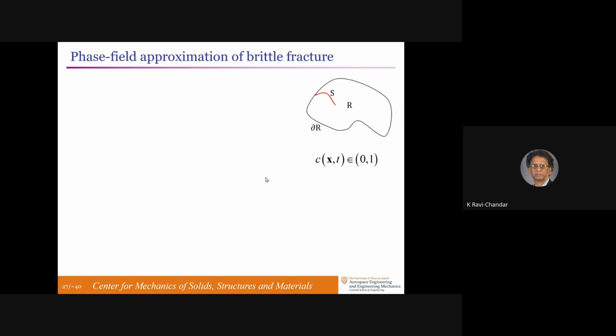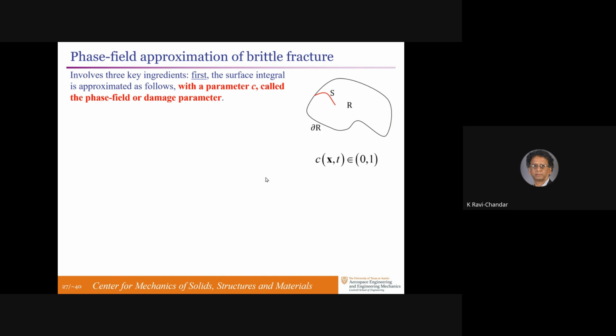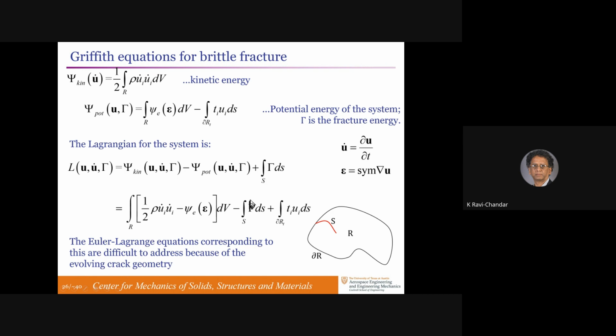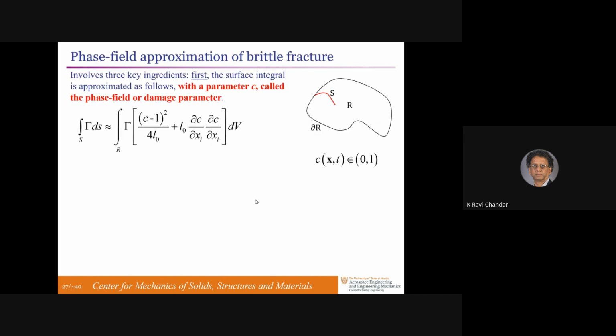But the idea behind the phase field approximation is threefold. First, the surface integral here is approximated by a volume integral. So instead of the integral of the fracture energy over the fracture surface, you do the integral of the fracture energy over a spread out smeared volume, where the volume is dictated by some intrinsic length scale L naught to be decided, and to introduce a parameter C, which will degrade this material from intact to a damaged material over some magnitude of the loading history, depending on what kind of formulation you do for the fracture energy penalty.